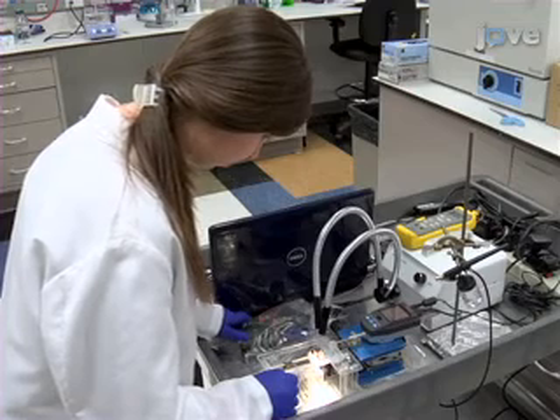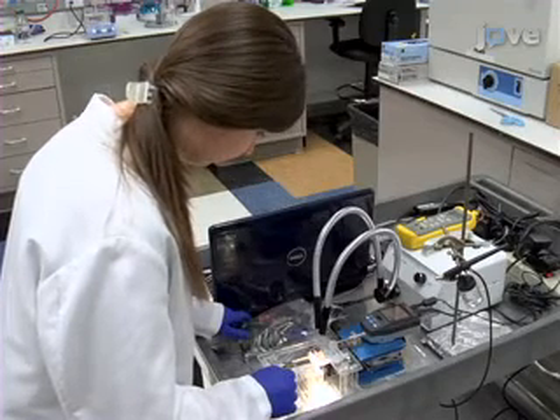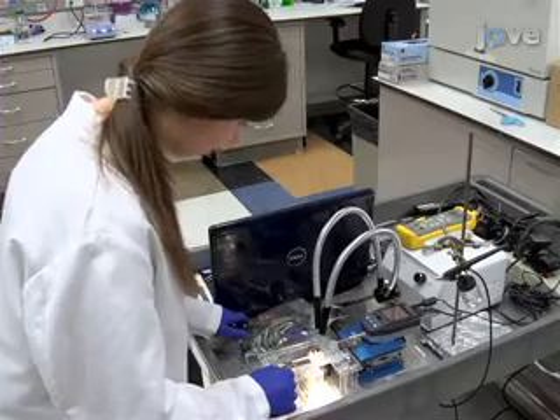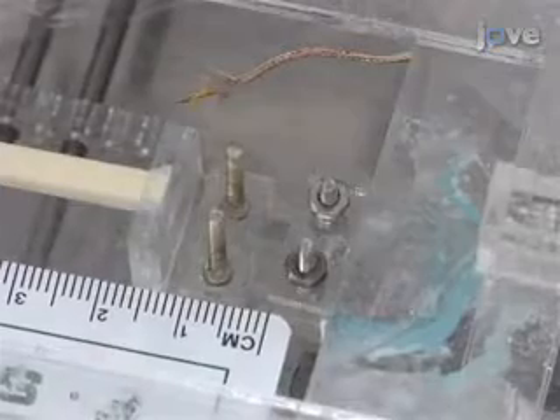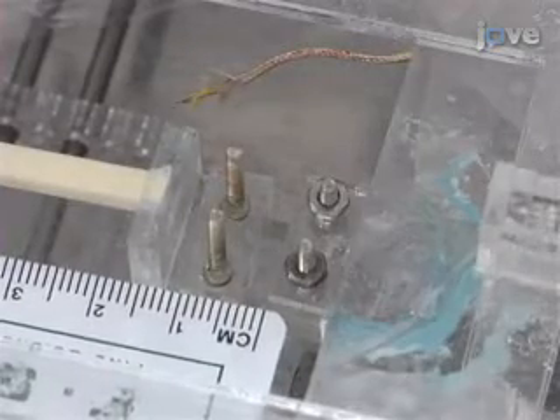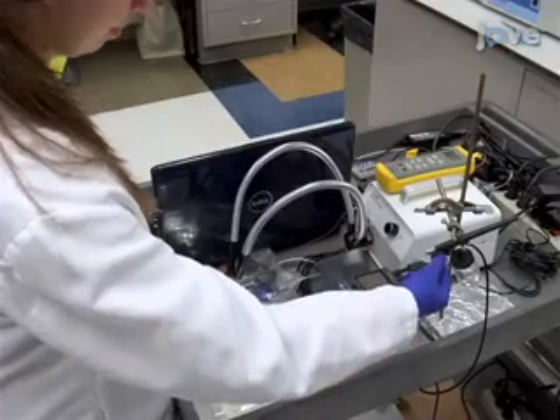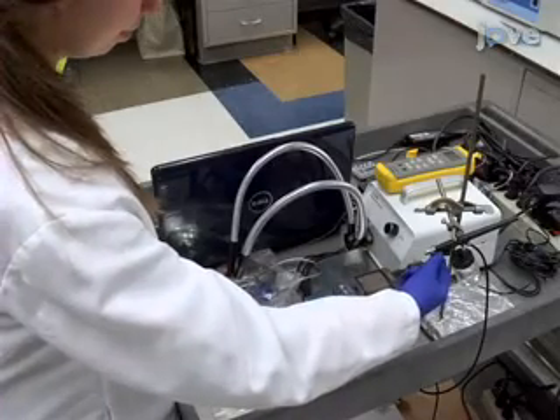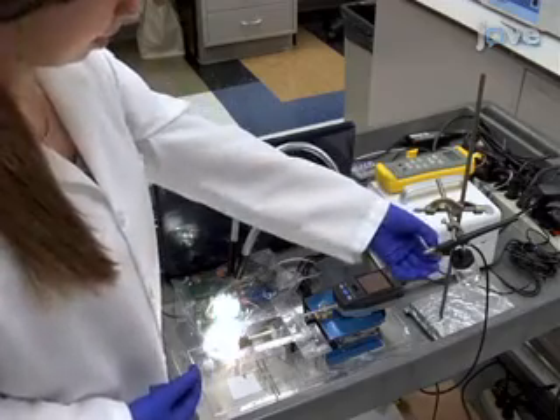While the probe is implanted in the cortex, prepare the microtensile tester by setting the drive rod to the zero displacement position of 3 mm from the stationary clamp. Also set the airbrush nozzle flow setting and the radiant heat source power setting to the values determined previously.